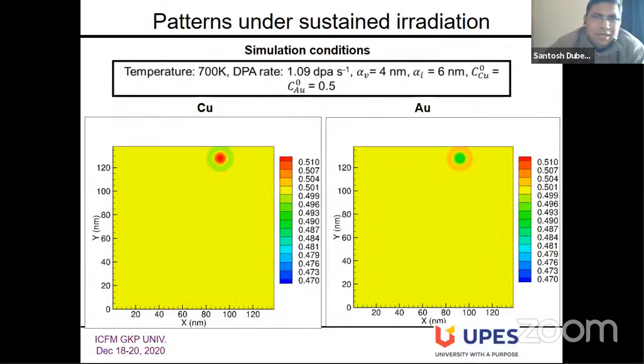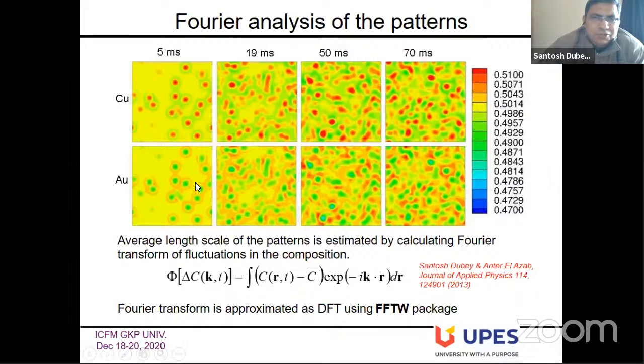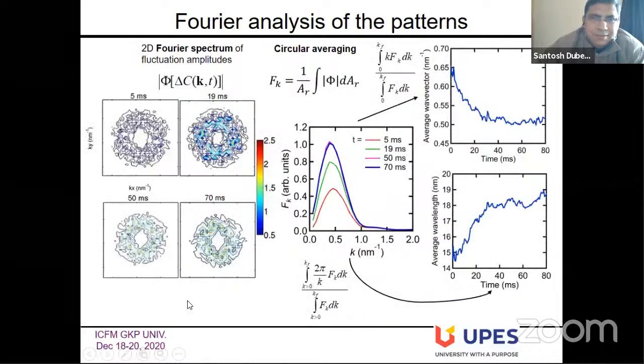I won't go into that. These are the simulations. I don't have time to show them, but this is the observation, the composition fluctuation that I get. I took the Fourier transform using the FFTW package, and found that patterns of around 19 nanometers stabilize in such a material. Depending on the irradiation condition, I can make fluctuations of smaller or bigger size.